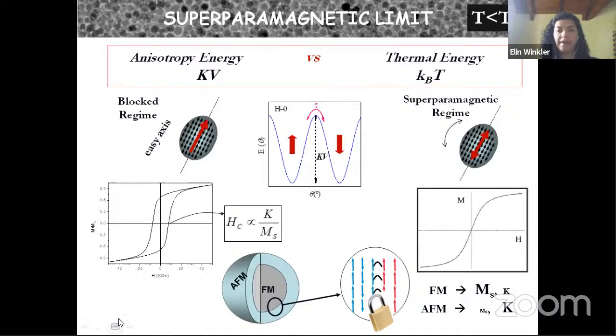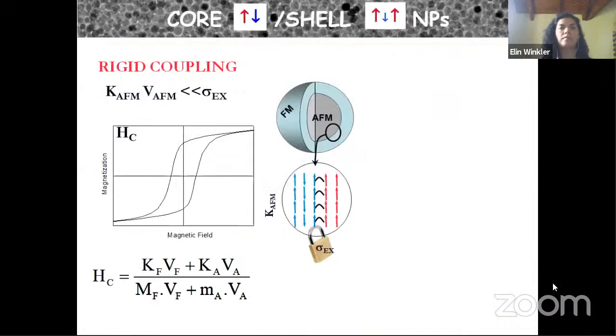Usually, the ferromagnetic material that has a very large saturation magnetization usually presents a small magnetic constant. On the contrary, the antiferromagnetic system usually has zero or very small magnetization, and it has a very large magnetic anisotropy. So combining both materials, we can fabricate a system with larger anisotropy. So we're going to talk in a little more detail about that.